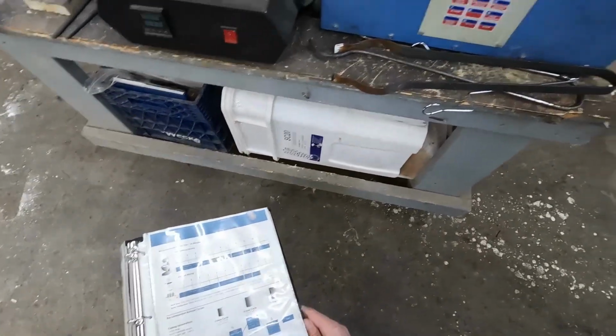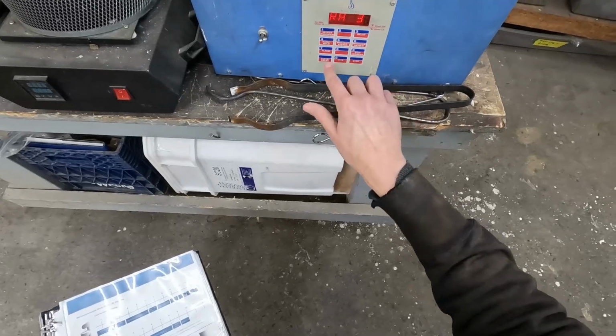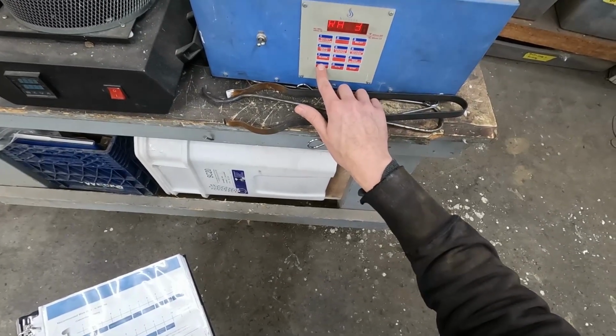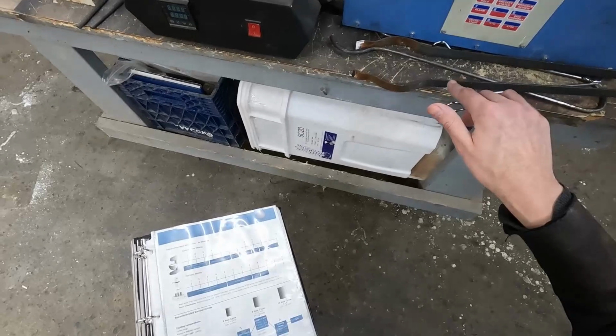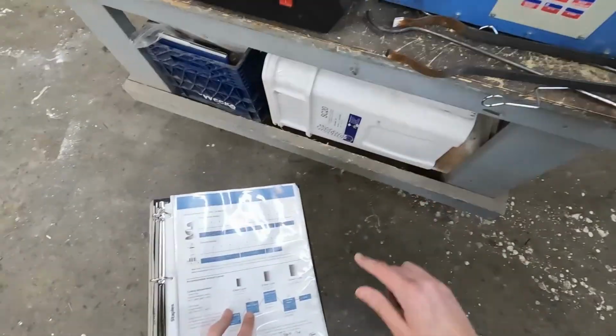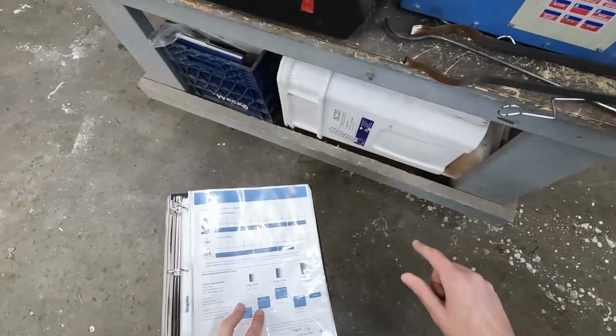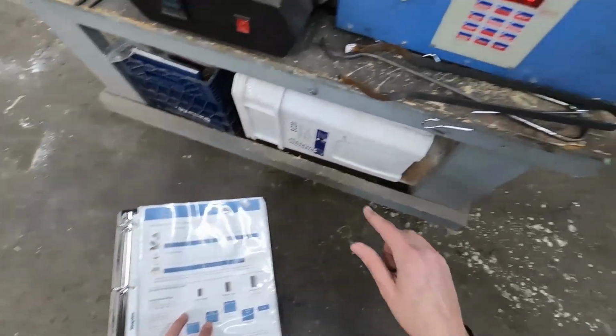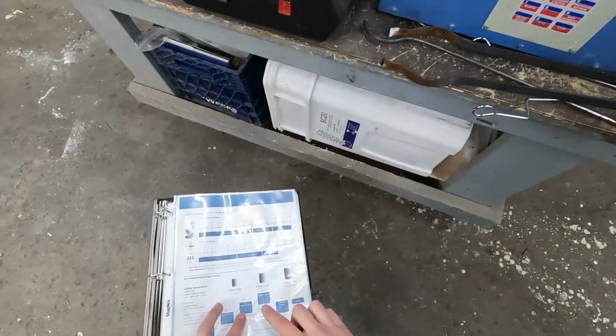hours. Ramp 3, still the same 540 Fahrenheit per hour rate. It's going to get up to 900 and hold it. In this case, we only have to hold for 1 hour. Now ramp 4,